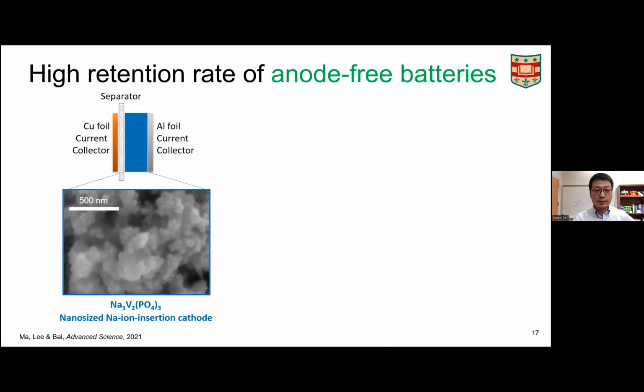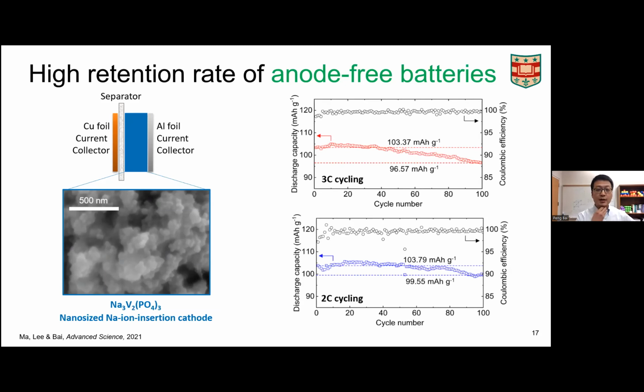And by doing this, we actually demonstrate the cycling performance of this anode-free battery. And these two charts show the cycling performance. The horizontal axis is the cycle number. The vertical axis is the discharge capacity. So every time, how much capacity, how many charges can you deliver, right? How much energy can you deliver? You can see that the energy you can deliver stays relatively constant, okay? So if you check the numbers, we actually achieve a record high performance compared with similar systems.